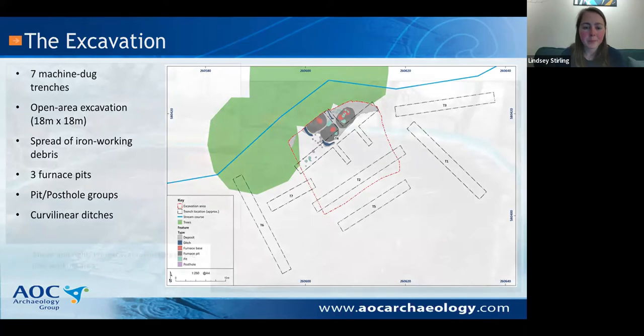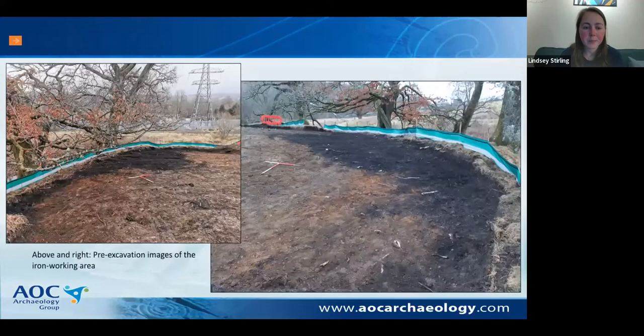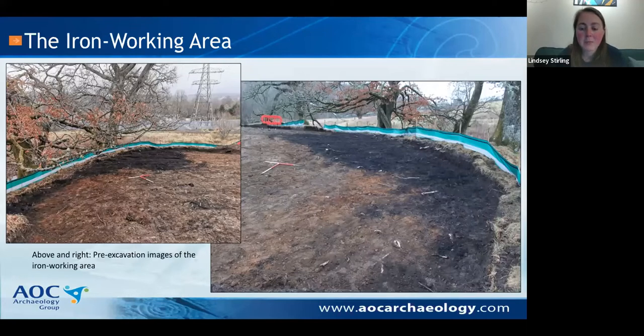So this is the main ironworking area. It was a clearly defined spread of really, really dark black silty sand. It contained lots of charcoal, lots of scattered clay fragments. This deposit lay over the top of pretty much all of the features on site. It's likely that this is just material that came from the furnace pits and was spread around the area after the abandonment of the site. And as you can see from these photos, the material spread down further below the trees, down to the stream bed as well.